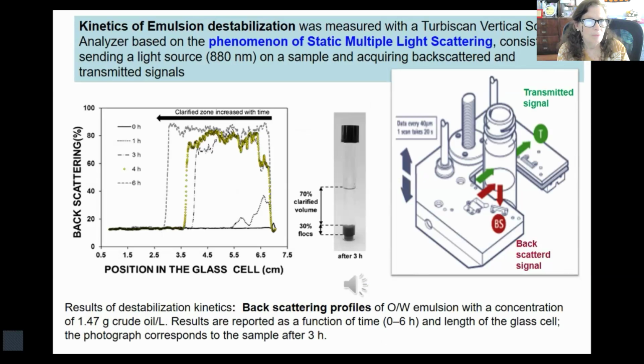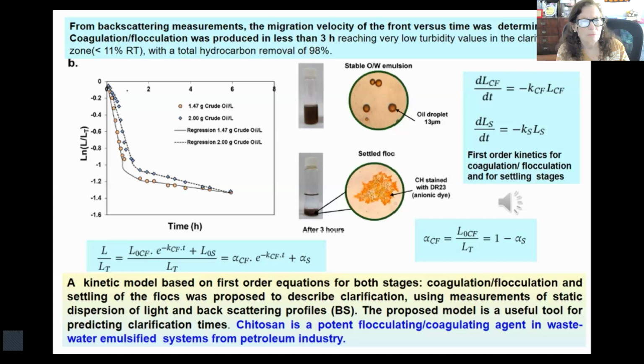Kinetics of emulsion destabilization was measured with a TurbiScan vertical scanning analyzer based on multiple light scattering by recording the backscattering profiles that show the increase of the clarified zone with time. A kinetic model based on first-order equations for both stages, coagulation-flocculation and settling of the floc, was proposed to describe clarification. Coagulation flocculation was produced in less than 3 hours. The proposed model is a useful tool for predicting clarification times. In conclusion, chitosan is a potent flocculating coagulating agent in wastewater emulsified system from petroleum industry.